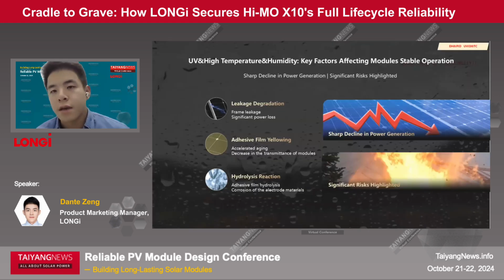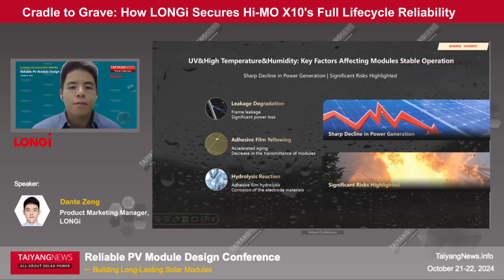So after the hotspot, we can turn to DH, UVID, and TC. I put them together because for the industry we already have some ability to solve them, we already know how they happen, and we have technology to get them done. But at the module level, from my own perspective, their damage is very close. It always leads to film yellowing, large power generation loss, and leakage. It's quite the same, but comes from different reasons: UV comes from light, high temperature comes from temperature, and humidity comes from the environment. But they always lead to similar degradation and similar loss.